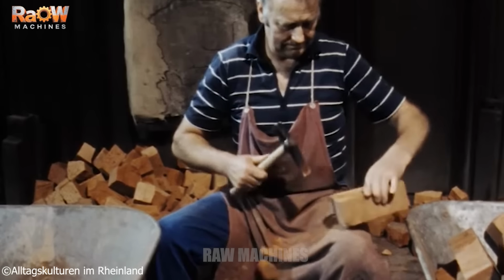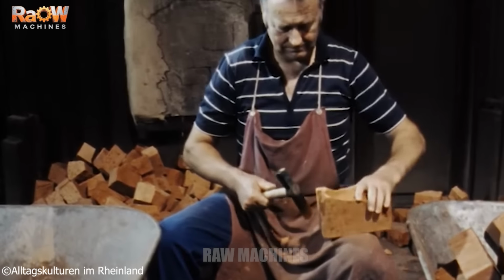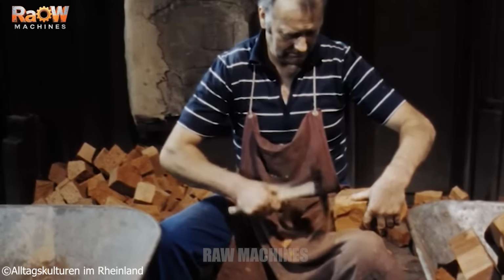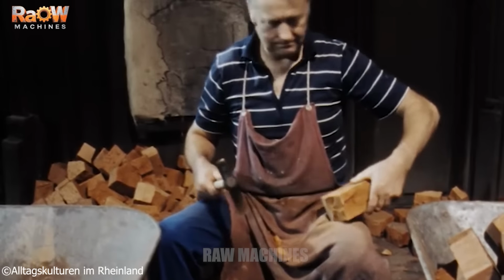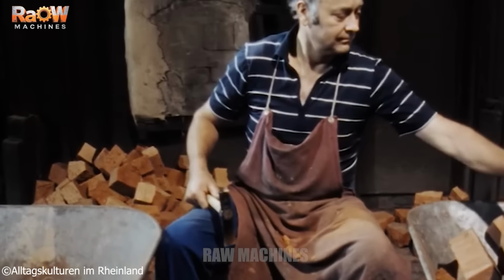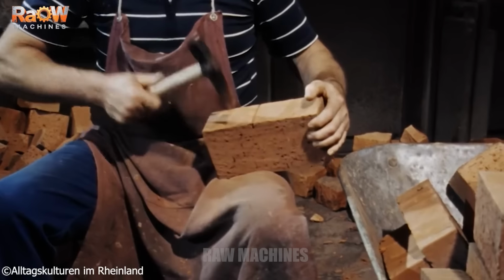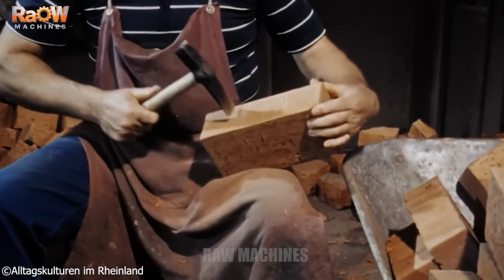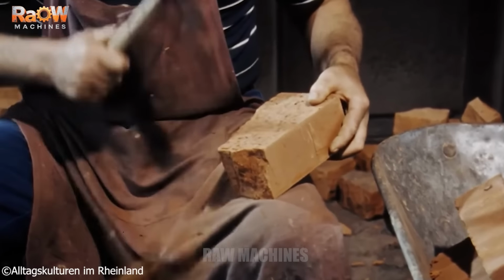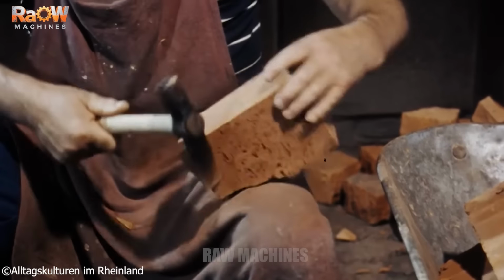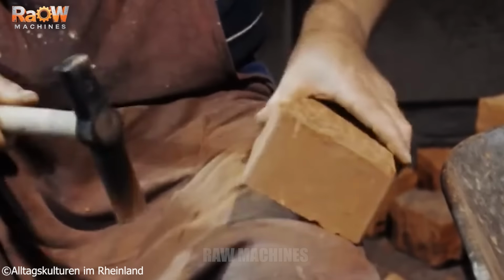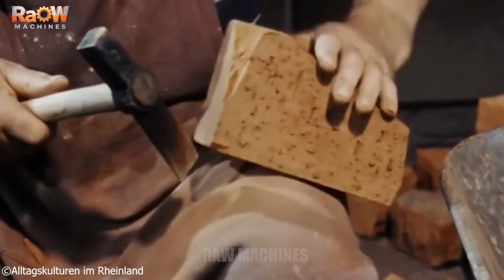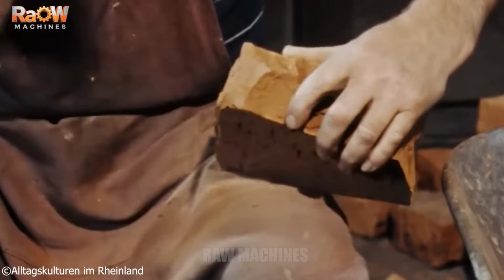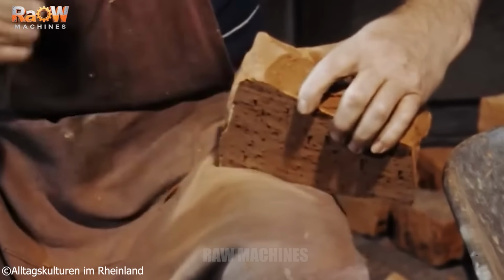The mold under construction belongs to a 5-bell peal, commissioned for St. Joseph Parish in Merzig. The core bricks are carefully measured and tapered to maintain an accurate circular profile. Partially fired bricks are preferred because they are easier to shape. Around the exterior of the core, a load-bearing iron ring is firmly installed, enabling the entire mold assembly to be lifted and lowered into the casting pit at a later stage.